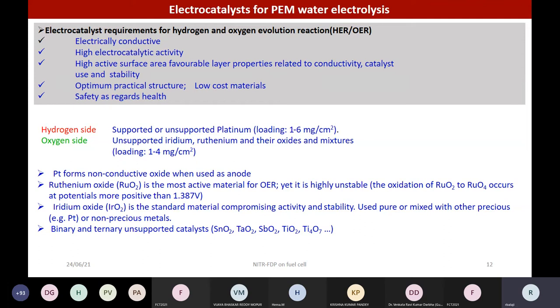Whereas on the oxygen side, you cannot use any carbon support because it will undergo corrosion. So you must use unsupported iridium or ruthenium based oxides, because you cannot use platinum as catalyst on both sides, unlike fuel cells. In a fuel cell, you can use carbon supported platinum on both sides, whereas in the case of an electrolyzer, you cannot use a carbon supported electrocatalyst at the anode side because of the carbon corrosion.